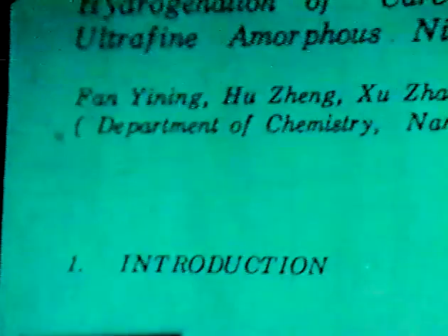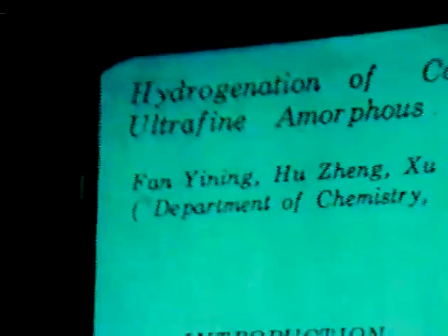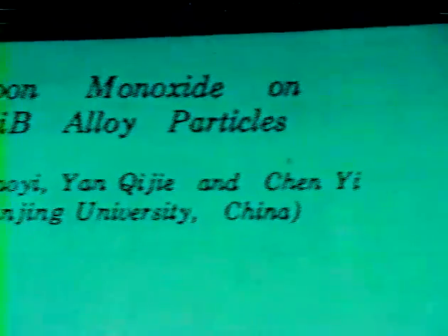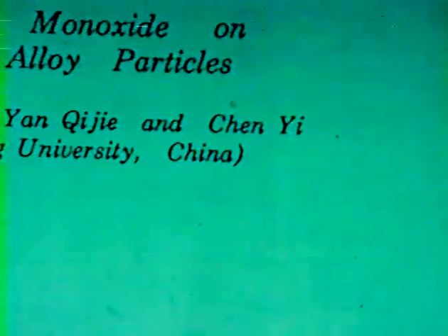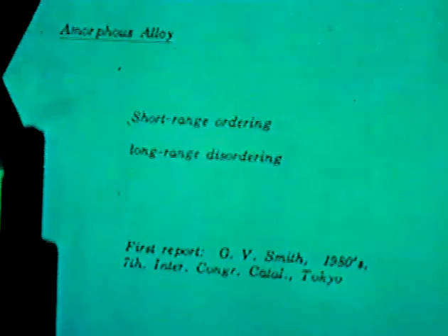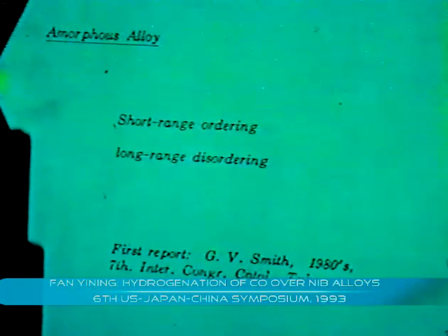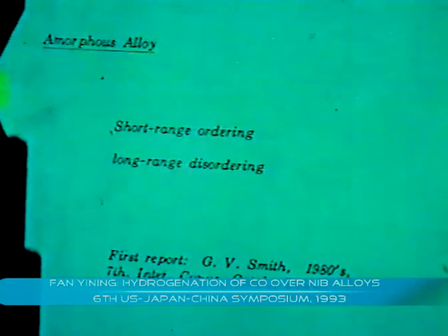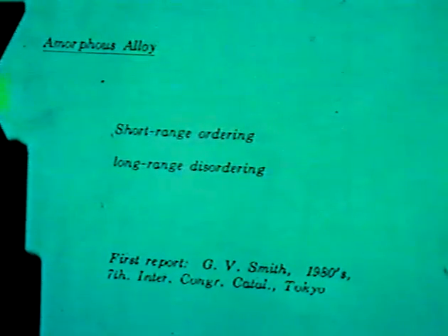Ladies and gentlemen, it's my pleasure to report our results on the hydrogenation of carbon monoxide on amorphous nickel alloy particles. It's well known that amorphous alloy has a short-range ordering and long-range disordering structure. In 1980, G. V. Smith reported the first results on the use of amorphous alloys as catalysts.